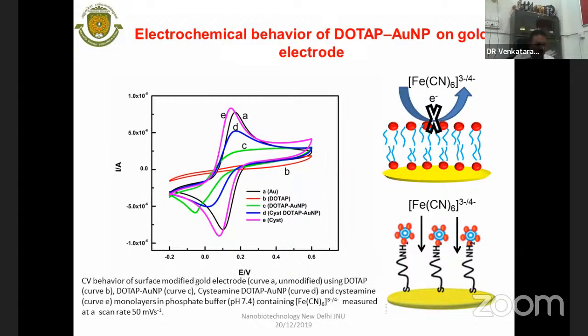And why we put this intermediate molecular layer in the presence of lipid is also another reason: if we put the lipid layer directly, we want to have a vesicular-like structure, but this vesicular-like structure will be broken if you put it directly on the solid surface. That is another idea of using this intermediate layer between the lipid layer and the gold electrode.